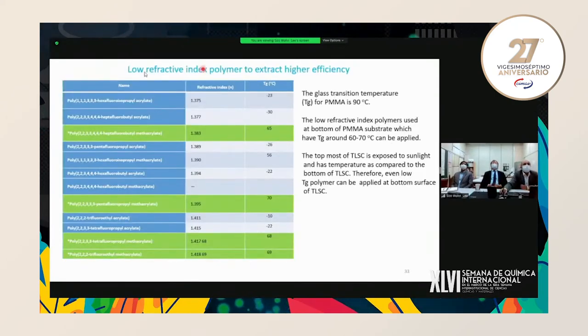Another component for LSCs is a low refractive index polymer. If we put this low refractive index polymer on the bottom of the LSC, we can increase the total internal reflections within the waveguide, and we can increase the efficiency. There are some low refractive index materials based on methacrylate, and these are below 1.5 refractive index. So we can use these materials.